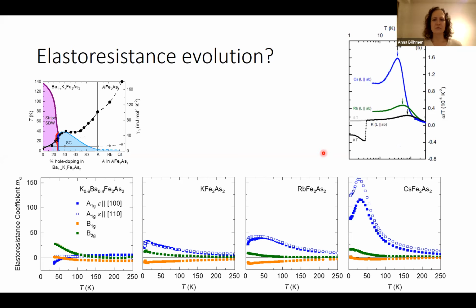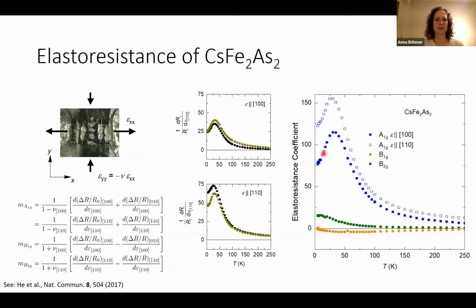Well, there are different experimental challenges. The challenge here is that one component is small, so to get it out accurately, that's not so easy. What you do in practice is you measure two directions and take a difference. And then it depends on misalignments, maybe. That's one challenge. We use a single sample for the two directions. That helps a bit. It doesn't affect the conclusion that the A1G component is dominant. It makes it difficult to get the exact temperature dependence, which depends on the exact size of the subdominant contributions.